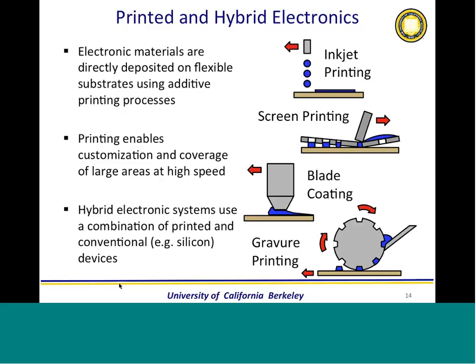And the recipe is coming from research labs where, you know, you anneal at 150 degrees for half an hour, or you anneal overnight, recipes that students conveniently find. But I always had recipes overnight, so I'm guilty too. And now there are companies that are commercializing not only the printing equipment, but the ink and the curing machine. For example, a company called Novacentrix has a very nice light curing, a very high power light that cures the silver ink in a question of seconds. So that becomes more feasible.